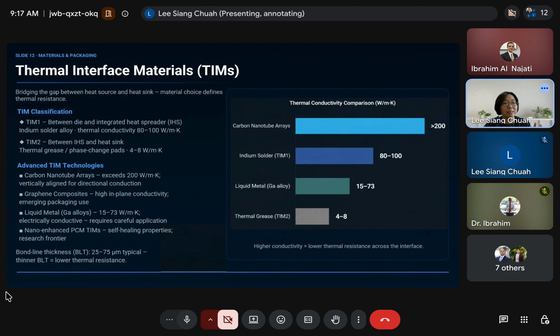Thermal interface material is a critical and often overlooked element in package-level heat management. It bridges the thermal gap between the components and determines the interface resistance. We have two tiers. TIM1 is the high-performance interface using indium alloy. And for TIM2, a thermal grease or phase change material.